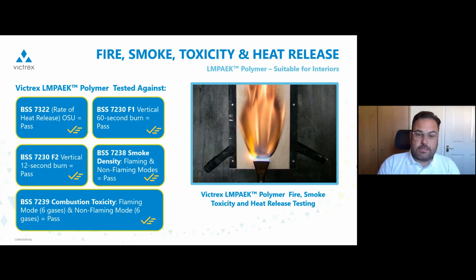The other 2 important tests are the vertical flame. So this is the 60 seconds and 12 seconds. What you do here is you have a strip of material of a certain thickness and you burn it, and what you measure is a couple of things. You burn it for 60 seconds, and what you are after is to see, when you remove the flame, for how long does the polymer still burn, and there is a requirement not to be above 15 seconds as far as I remember. Excuse me. The other thing that you could test is the flame length, how much of that specimen was burned, and then if you have any dripping of that polymer, if it extinguishes within 3 seconds or not.